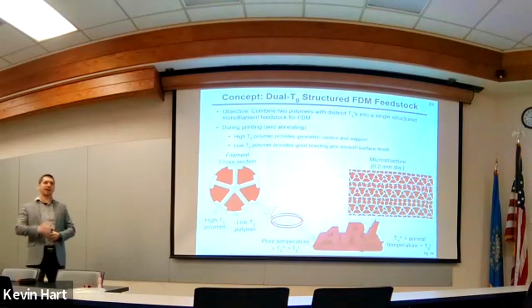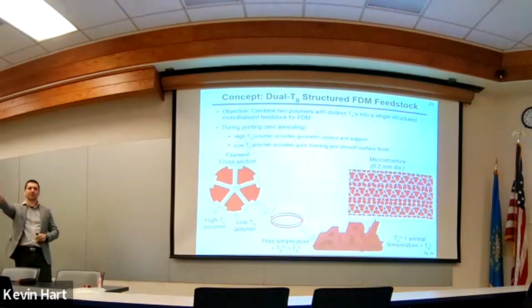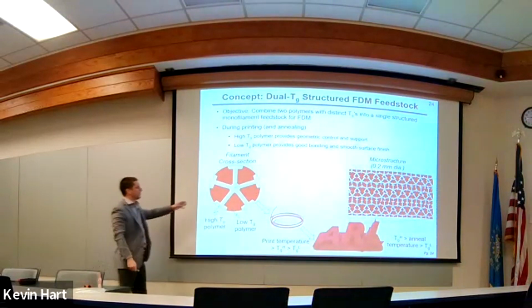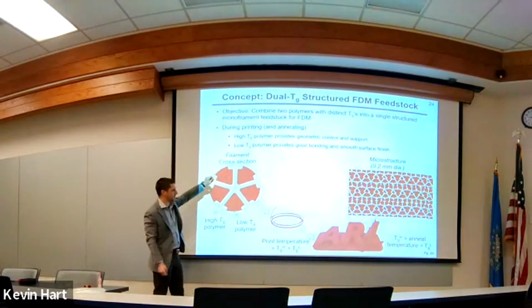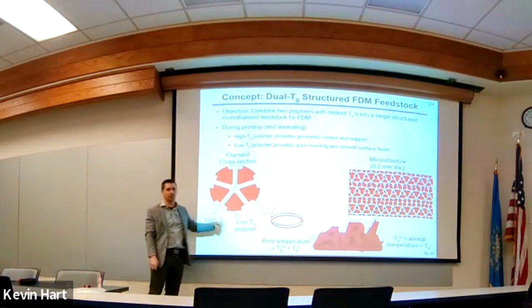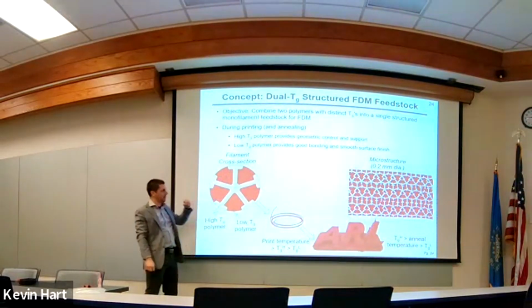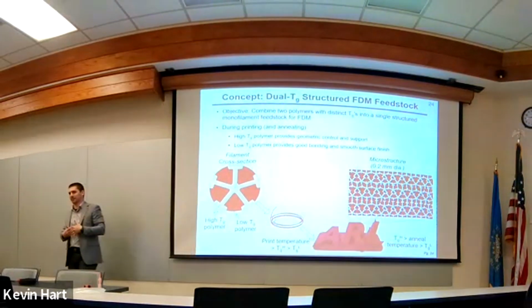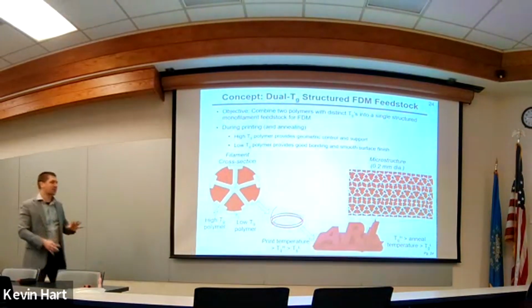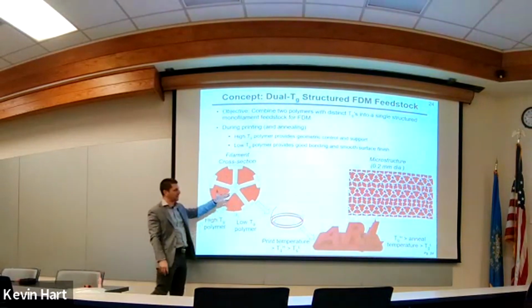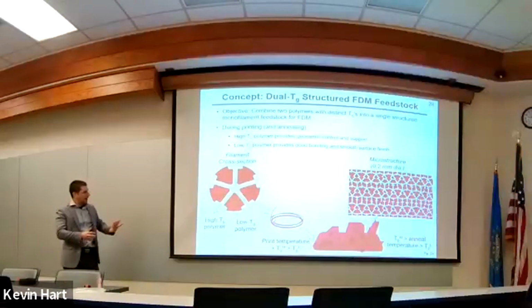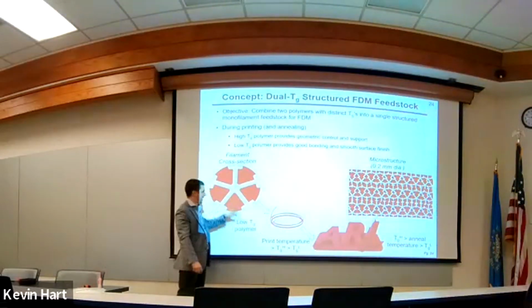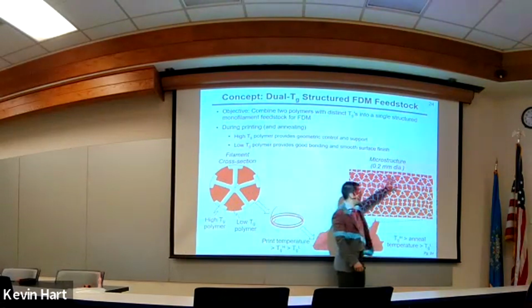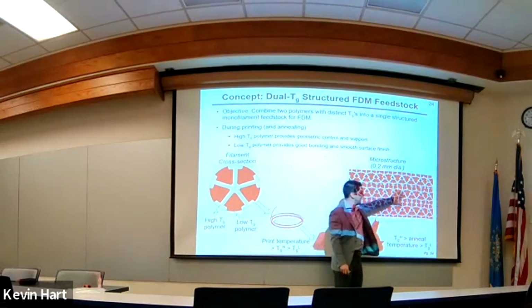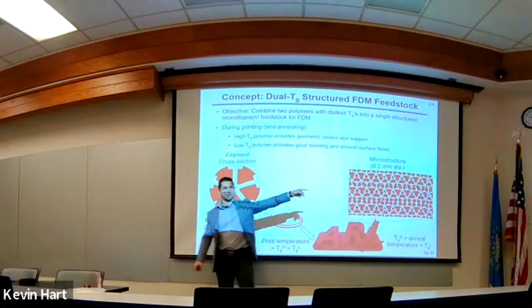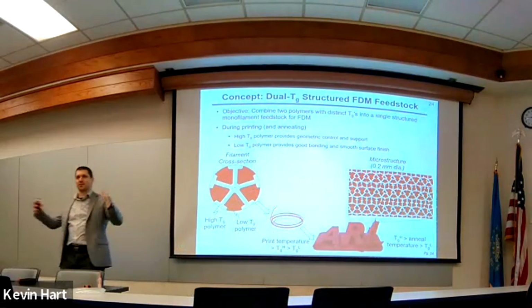And this idea is to use a filament in the 3D printing process that's actually made of two different polymers. So in this particular example, you might have a red portion of the 3D printing filament that is ABS, what we call a low glass transition polymer, and the white portion of the 3D printing filament that is a high glass transition polymer. In this case, we use polycarbonate. So the glass transition temperatures of these two different polymers vary by about 50 degrees C. And the idea now is that we're going to take this filament and print a structure using it. And so the mesostructure of that material might look something like this. You got all this white that is polycarbonate, all this red that's ABS.